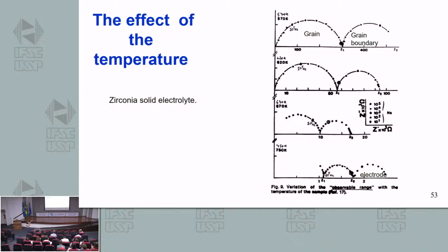So the resistance is the resistance of charge transfer, electron transfer, and the capacitance is the capacitance of the double layer. This in zirconia is very well known and accepted. So if I have an ionic conductor like a lithium glass conductor or sodium conductor, it may be indicative that I will have, at very low frequencies, some kind of electrochemical reaction. But we should avoid it.